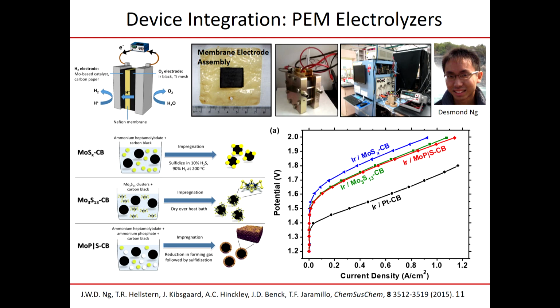And we said, well, let's make our own home-built water electrolyzer. So this is what it looks like, a very modest 5 square centimeter thing. This is Nafion, conventional plastic that used to conduct protons, carbon gas diffusion electrodes, and he basically put these inks of non-precious metal catalysts and wanted to compare them versus platinum. So he is now running these at more commercially relevant current densities of 1 amp per square centimeter. And you can see that the iridium platinum polarization curve is definitely the best of the bunch. It's the one that gives you the 1 amp at the least amount of applied voltage.